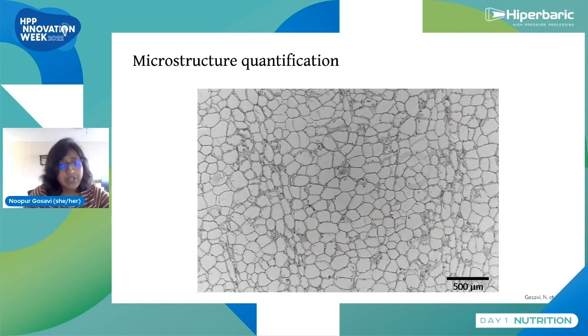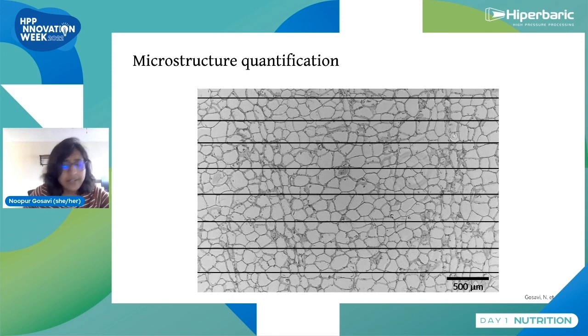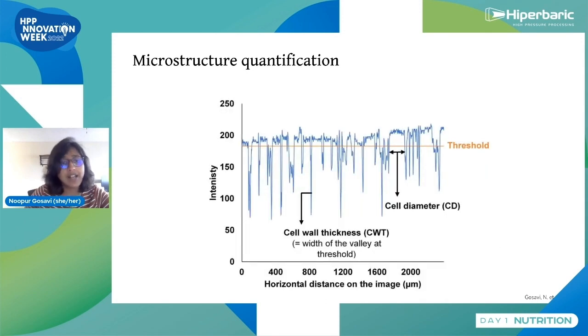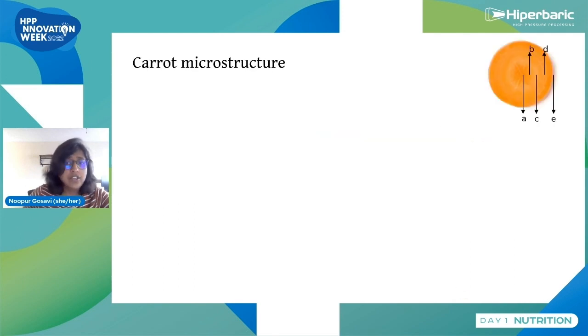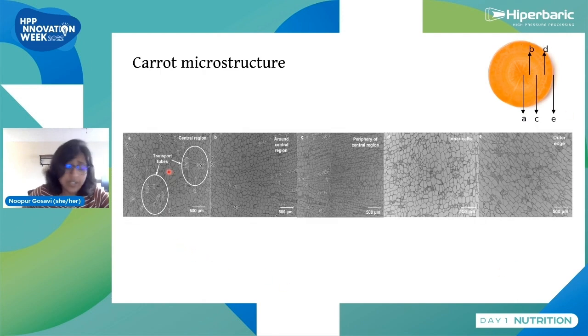So we look at the microstructure of these vegetables. Now, given a texture or microstructure image like this, we draw hundreds of lines across and we obtain a graph of intensities of the pixels across the image. And this helps us quantify the cell diameter and the cell wall thickness. So if you look at baby carrots, we observed the image at 5 different points. And we looked at the texture, the microstructure. And you'll see that the cell size varies immensely throughout the texture, throughout the slice.